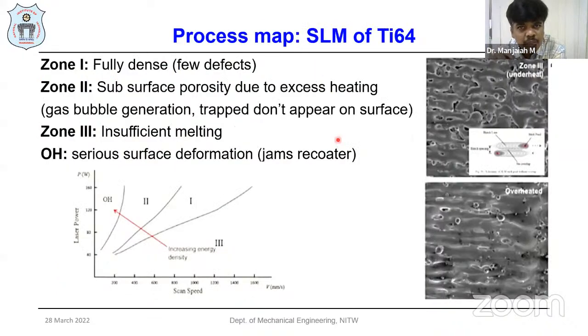And if you see with respect to the process map, selective laser melting of titanium alloys, you see in the graph and on the right-hand side, the SEM images are reported here. We require a process window for whatever the material may be, either aluminium or stainless steel or maybe the titanium alloy. The process window means the process parameters to have the proper energy density to melt and solidify the materials. See zone 1 to zone 3 as well as the melting zone. Going with either the laser power or the scan speed, there may be overheating, or insufficient melting, or it may create serious surface deformations that will affect the recoaters or the rollers or the blades.